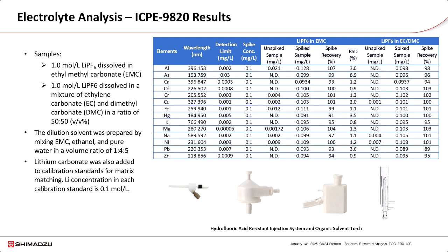This is a very challenging sample because electrolyte of lithium-ion secondary batteries are typically composed of lithium hexafluorophosphate dissolved in an organic solvent, requiring an injection system for organic solvent. However, lithium hexafluorophosphate can hydrolyze to generate hydrofluoric acid, which attacks glass-based injection systems commonly used in ICP-OES. Lithium is an easily ionizable element that also compromises analysis results.